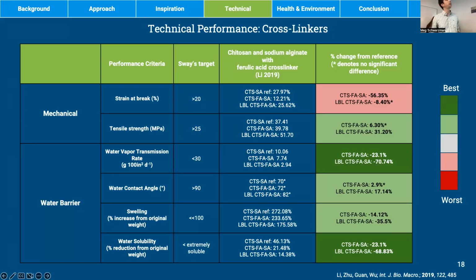You'll notice too that on the far right, the percent change, there's two different data points provided. CTS FA-SA is our chitosan sodium alginate cross-linked with ferulic acid. This is synthesized via direct mixing of all of the components at once. Furthermore, they explore this LBL one, which is a layer-by-layer synthetic approach in which the sodium alginate layer is first cast, allowed to dry, and then a chitosan ferulic acid mixture is spread across the top of that and then allowed to dry furthermore.